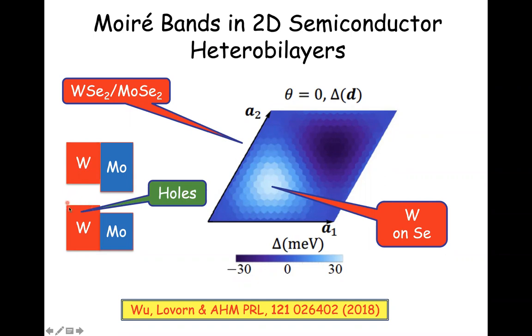And so if you just make a few holes, that's the case that has been studied most often, in the valence band of this bilayer, all of those holes will go into one of the two layers. And therefore, near the Fermi level, there's basically only one state for each momentum. And so when you form a Moiré pattern, like I was showing you for the graphene bilayer case, every property depends on the registry between the layers. And here, since we have only one state at each momentum, the only thing that can change with position is the energy of an electron with that momentum.